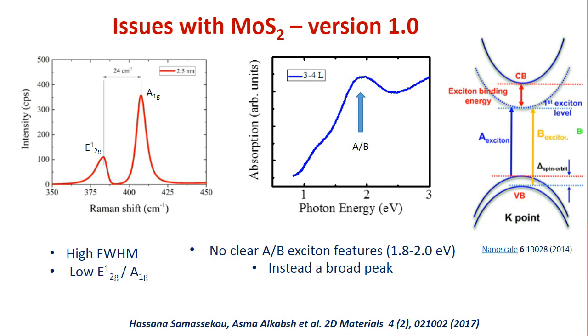Now, what kind of disorder could we have? There was a lot of speculation that our MoS2 sputtering process is causing lots of sulfur deficiencies. So we don't have all the sulfur that we need to make a stoichiometric MoS2 film. So it is sulfur deficient MoS2. That was our hypothesis. And again, we used the Shimadzu spectrometer to check these hypotheses.